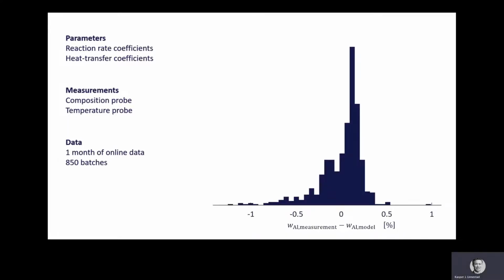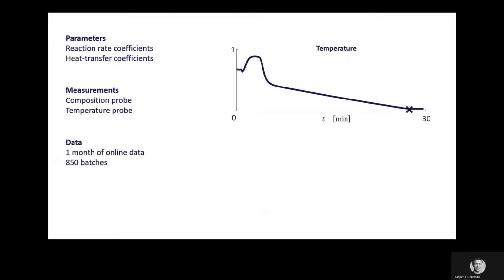Here we can see a histogram of the error distribution for the aluminium concentration before model fitting. The mean error is not 0 and the distribution is relatively wide. After model fitting, you obtain a narrower error distribution with a mean close to 0.